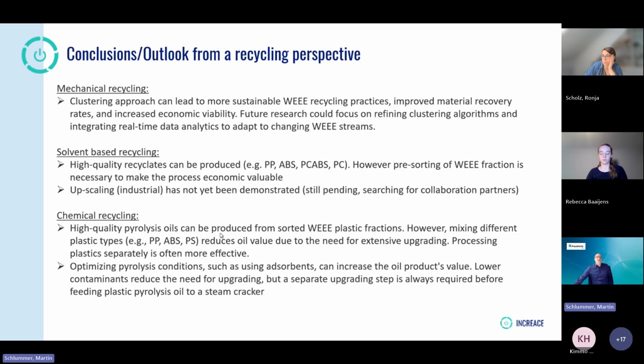For chemical recycling, we can produce high quality pyrolysis oils from sorted WEEE plastic fractions. However, the mixing of different plastic types reduces the oil value, and therefore we need extensive upgrading. Processing plastics separately is often more effective. Optimizing the pyrolysis conditions, such as using adsorbents, can increase the value of the oil products. Lower contaminants reduce the need for upgrading, but for sure a separate upgrading step is always required before feeding the pyrolysis oils into a steam cracker.